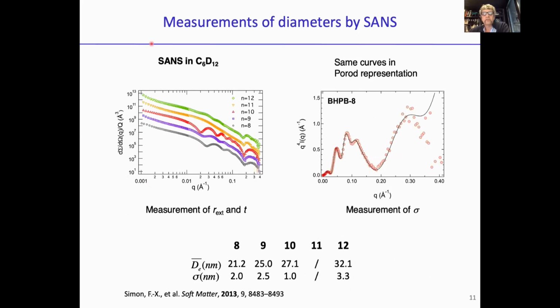So we can do this for all the species I showed you, for 8, 9, 10, and 12 carbon. And you can see right from these curves that when the diameter increases from 8 to 9, then the oscillations get narrower, which is correct. And also when the polydispersity increases, then the oscillations are attenuated.